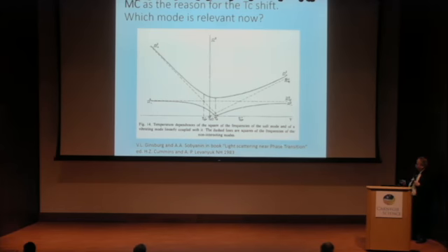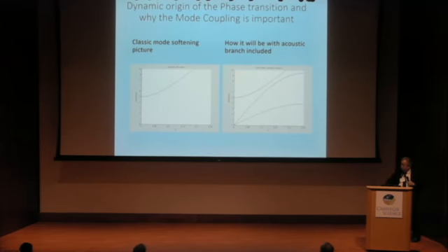It was demonstrated, for instance, that if we have two modes, one of which is soft and the other is not, and the one is temperature independent, the other one is soft. So at some moment when they want to intersect, the second one is becoming soft, and finally the result is condensation not of the soft mode, but of some other one, either the one that was not soft originally or some mixed. And then if you will go and consider just a simple picture of dynamical origin, classic mode softening picture, let's say,